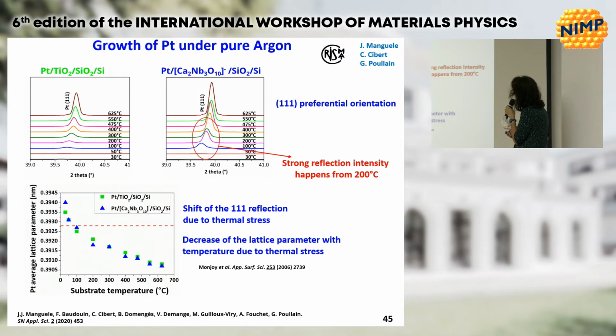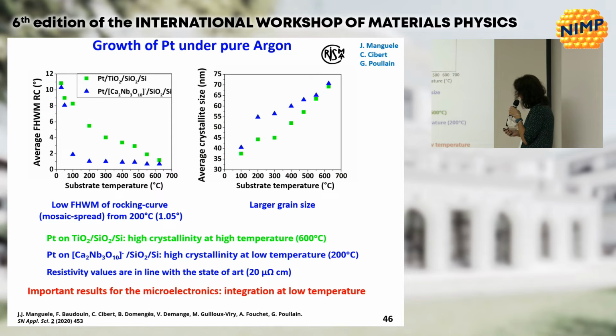But the most important result is here. We already have something on the nanosheets from 200 degrees Celsius, versus the same result at about 600 degrees with the normal substrate. So this is a very important result for microelectronics. And also, if we look at the rocking curve, we have something very low for the material deposited on nanosheets. And this is also something really important for microelectronics. Also, the platinum presents larger grain size when grown on nanosheets.